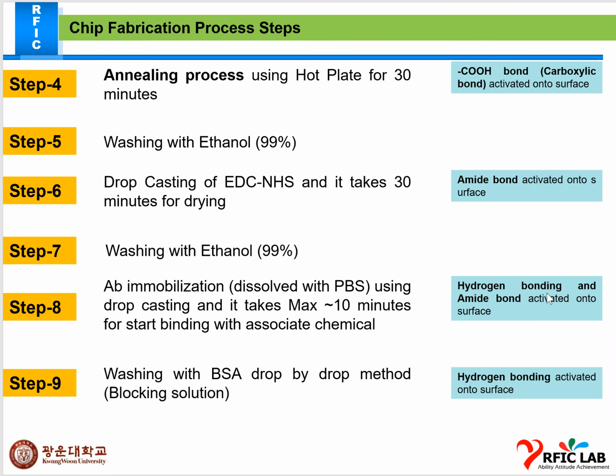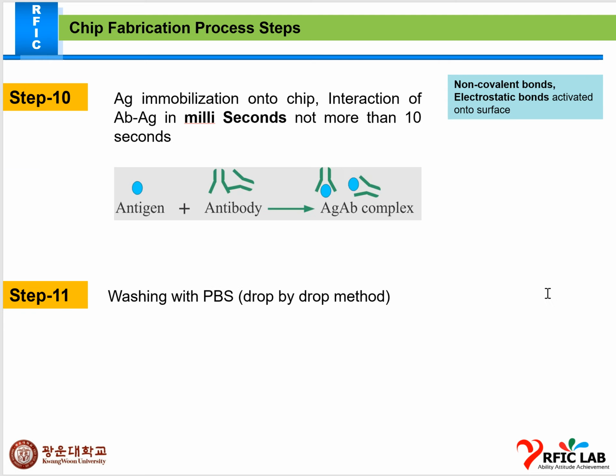After the deposition, I have to use the hot plate for the annealing process, and then wash with the ethanol, and use EDC/NHS for the immobilization, amide bond formation, and then hydrogen bonding. Then washing with the BSA, and afterwards normal washing with the PBS, and then the antibody-antigen complex combines in milliseconds, or not more than 10 seconds. Then washing with the PBS by the drop by drop method, and then we have to measure the capacitance for different concentrations of the antigen.